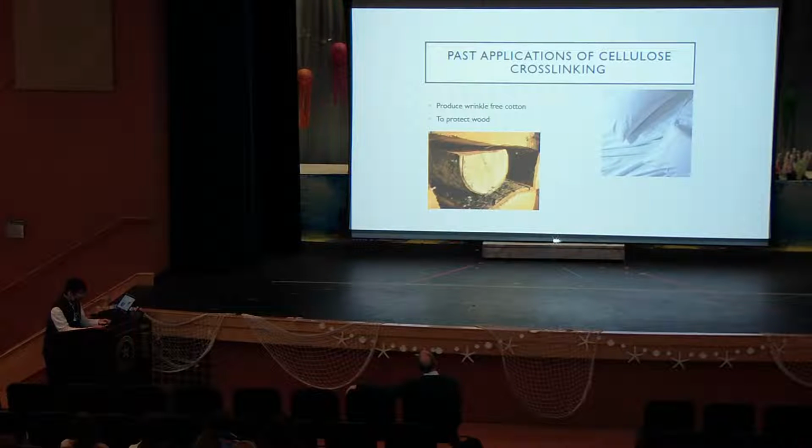This leads to a bunch of related phenomena, namely decreased wet strength, since you aren't dealing with strong intermolecular interactions anymore, just steric hindrance and the natural tensile strength of the paper fibers, or cotton fibers. And the volume expansion and a conformational change that come from the impingement of water. As the water leaves, this conformational change becomes locked in, usually resulting in wrinkling, because that's a lower energy state than a completely flat sheet of fabric.